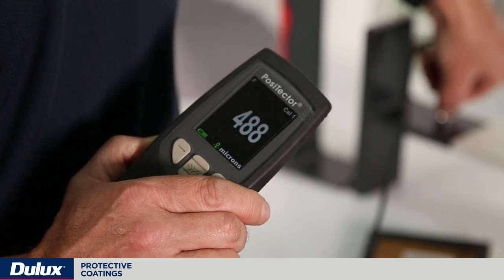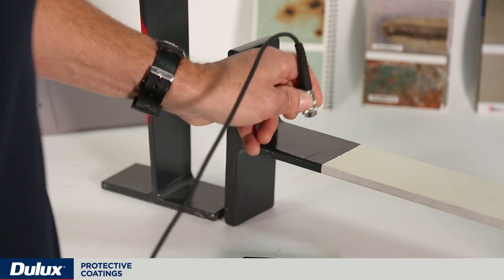I'm achieving readings of 450 to 500 microns in this protective coating system, which forms a protective layer to stop moisture and contaminants getting through to the mild steel substrate. This is completely different to a decorative system, which may be applied in coats of between 20 and 30 microns per coat — so in a three coat decorative system, the average dry film thickness could be 60 to 90 microns. That's not going to give much of a barrier in a corrosive or industrial environment. This is why it's essential to use protective coatings over mild steel, galvanizing and concrete in industrial and corrosive environments, where it's absolutely important to have the right film build, the right coatings and the right surface preparation to ensure long-term protection in accordance with the standard.